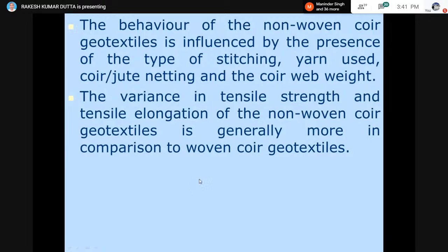Now the variance in the tensile strength and the tensile elongation of the non-woven coir geotextile is generally more in comparison to the woven coir geotextile. This is true because the woven geotextiles are manufactured from yarn prepared by some machine, so their quality control is better. Whereas in the non-woven geotextile, only loose web is put together and the stitching or needle punching is done in one direction or the other direction. That is why the variation in strength is going to be more in case of non-woven in comparison to the woven types of geotextiles.